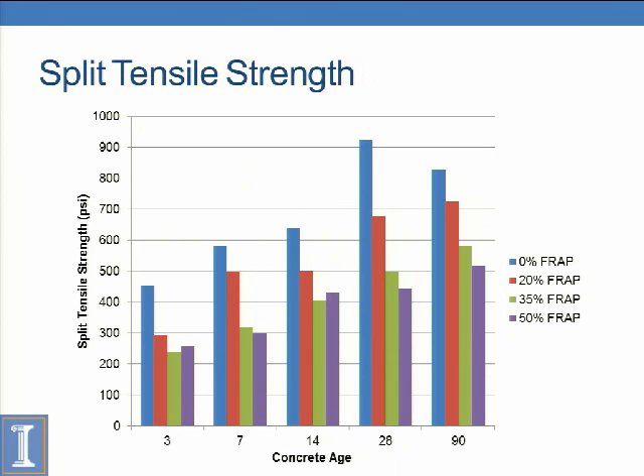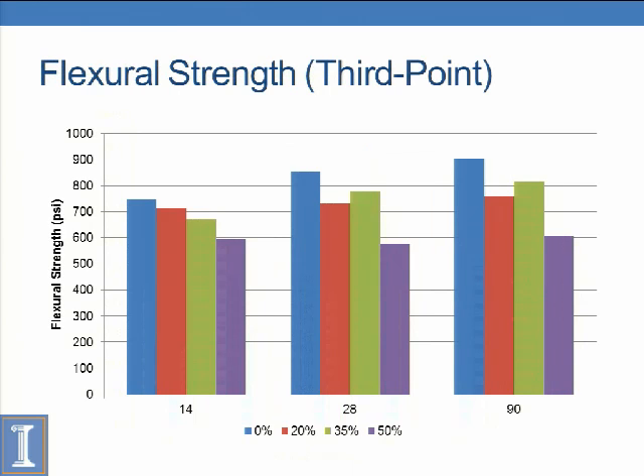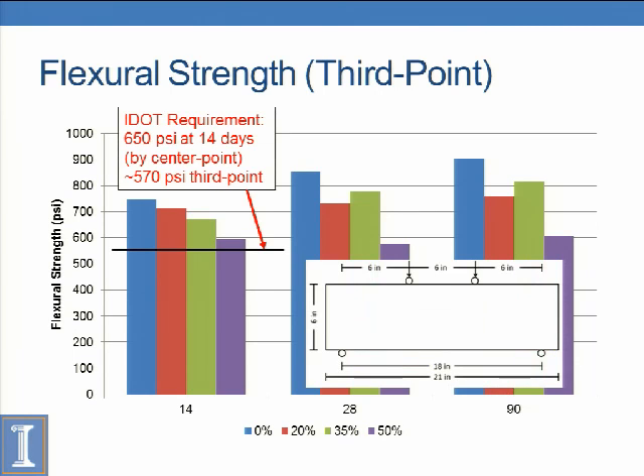So that's important to note is we need to meet IDOT strength requirements. Split tensile strength was a similar behavior with reduction in strength with increasing FRAP. Similar with the flexural strength. Again, we have just reductions. Not sure why we had a higher 35% there. It was interesting behavior that we were not expecting. But what to note here is IDOT has a flexural strength requirement of 650 PSI at 14 days.